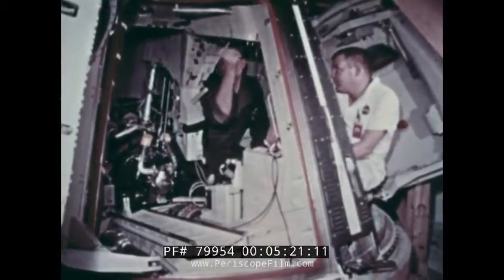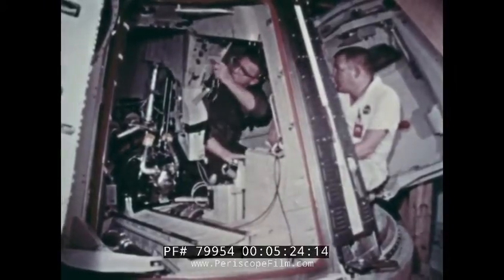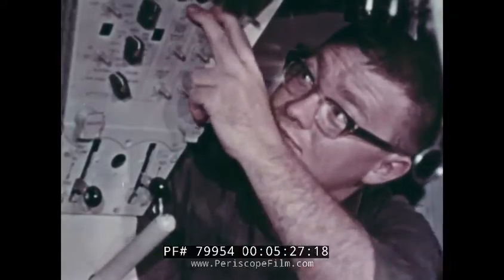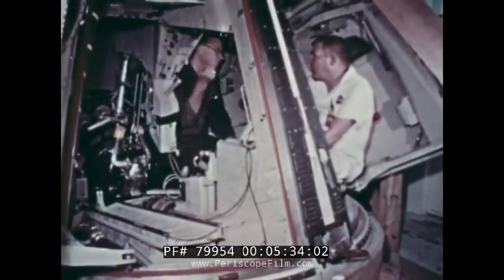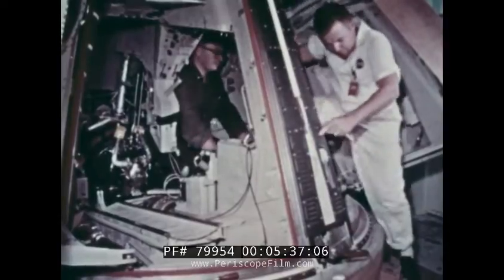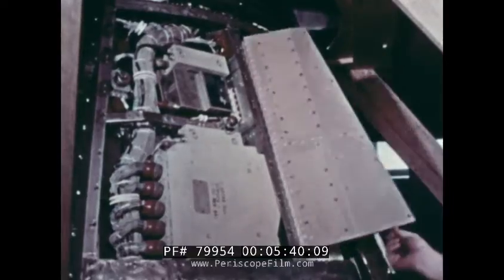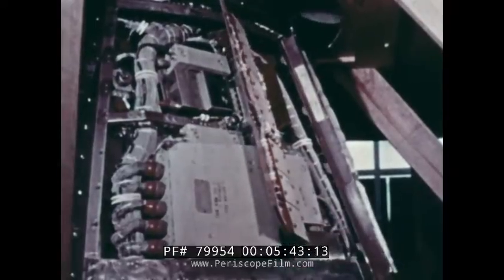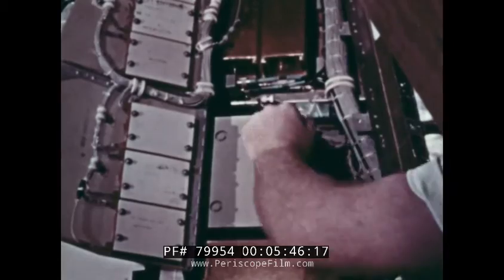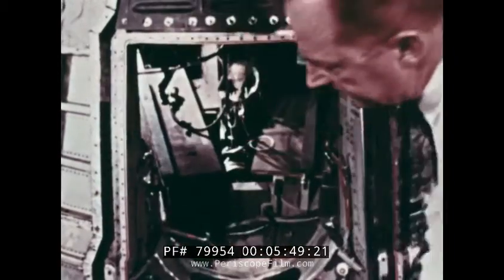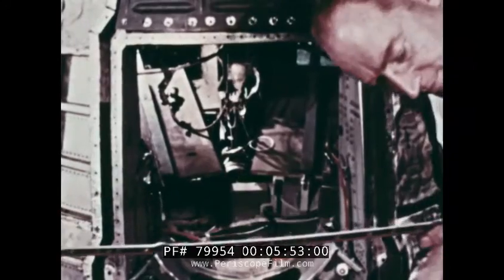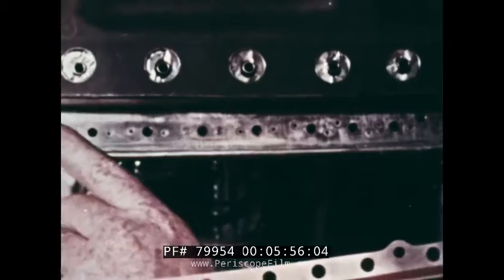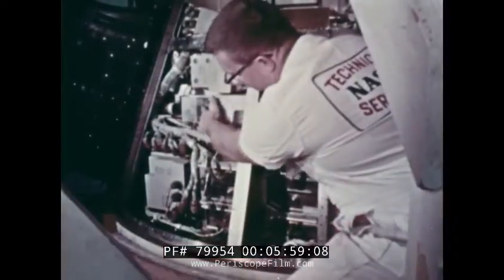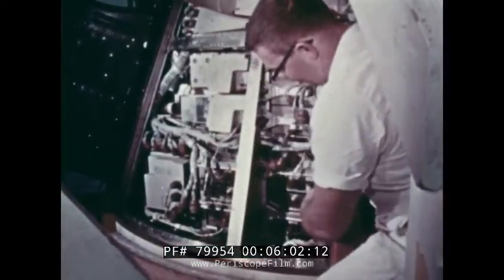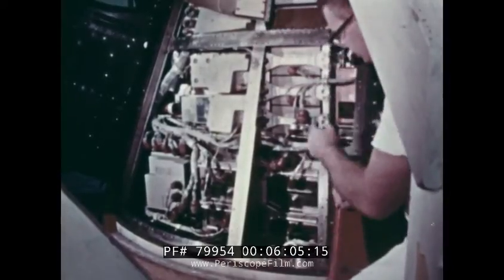After this sea test, Static Article 5 was returned to MSC at Ellington Field for further examination. The post-test inspection revealed several areas in which redesigning or correction was needed. The lithium hydroxide charge was found to be nearly 5 pounds overweight from absorbed water. The short circuit in the electrical system was traced to imperfect potting, a corroded umbilical plug, and leaking connectors. The battery straps showed an excessive amount of corrosion. Corrosion was also noted on the access door seal to the environmental control system. These problem areas were documented, and the necessary corrections to the spacecraft equipment were performed by McDonnell Aircraft.